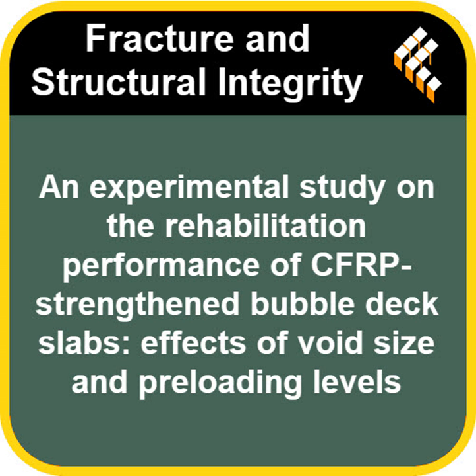But don't let that fool you. It boasts an impressive tensile strength of 3,500 megapascals. Huge pulling strength. Massive. And an elastic modulus of 230 gigapascals, which tells us it's incredibly stiff, it resists stretching. These sheets were then externally bonded to the bottom surface of the concrete slabs, essentially glued on. Using a specialized two-step epoxy system, they followed well-established guidelines for these types of repairs to ensure a good bond.